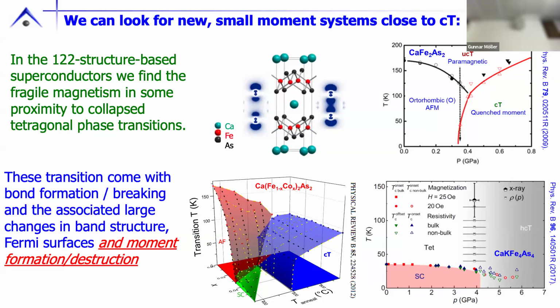Peng Cheng? Yeah, basically saying the moment collapses. Now, when that happens, you can imagine that when I'm changing the bonding, when I'm depopulating this anti-bonding orbital, I'm changing the bands. And with a dramatic change in the bands, of course, stuff changes. Now, you don't know a priori whether you'll go from magnetic to non-magnetic, non-magnetic to magnetic, or nothing. But it gives you large tunability.